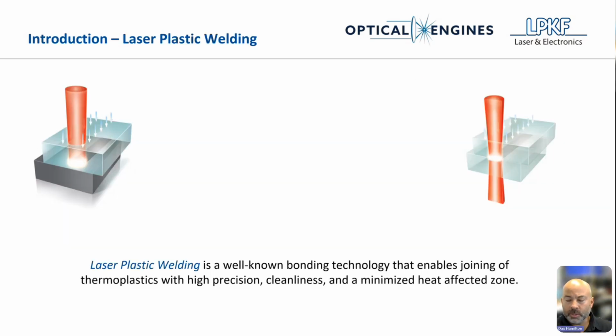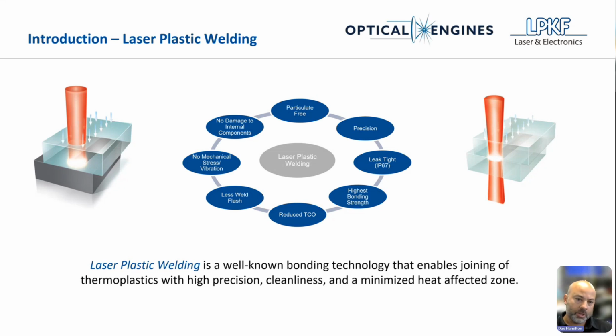Laser plastic welding is a very well-known bonding technology and enables joining of thermoplastics with high precision, cleanliness, and a minimized heat affected zone. Some of the advantages here: it's particulate free. You're not introducing any consumables like glue, or, with ultrasonic welding, vibrating 2 pieces together, so there's potential for particulate generation. It's very precise. You can get leak-tight seals. It's one of the highest bonding strengths of any of the plastics joining technologies, over 95% of the base strength of the material. Less weld flash is produced by laser plastic welding. No mechanical stress or vibration is induced, and no damage to internal components, which leads to a reduced total cost of ownership.